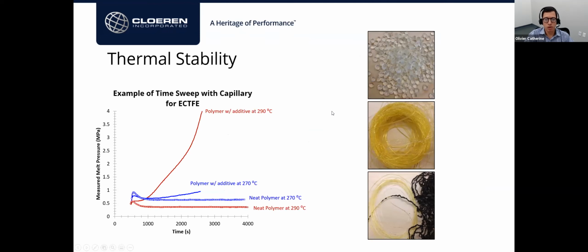Another great feature of the Rheometer is being able to observe how stable materials are. And sometimes it's a fight because we have material that tends to degrade before we're done with our viscosity measurements. But I can also use the Rheometer as a device to determine if the material is stable or not. So here's an example of another fluoropolymer, a partial fluoropolymer and a chlorinated fluoropolymer, so ECTFE. This ECTFE material, in fact, is quite stable thermally.